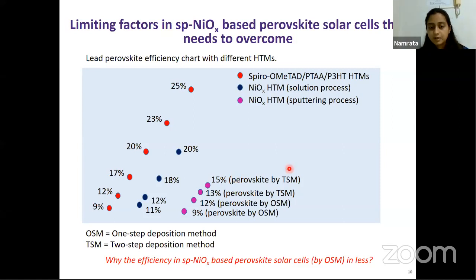And of course, changing the composition can change the efficiencies. So now the question we need to address is why the efficiencies are low for the sputtered nickel oxide case, in order to further enhance and increase the efficiency of sputtered nickel oxide based perovskite solar cells.